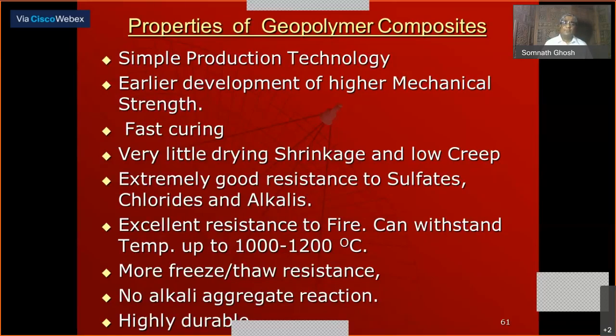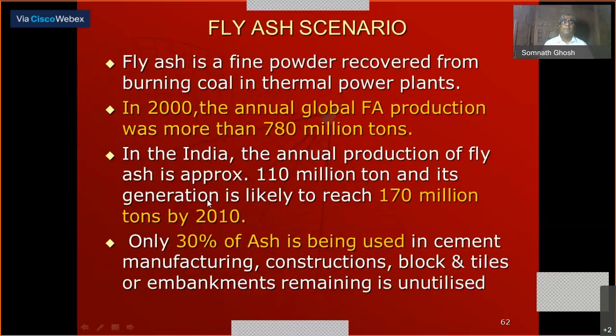The excellent resistance to fire, it can withstand that. Many PhD students worked on it, and ultimately found that it is good up to 1000 to 1200 degrees centigrade temperature. The freeze-thaw resistance is very good, and also alkali aggregate reaction, and it is highly durable. So all these things are much better than the conventional cement because of the polymeric structure. It is CSH gel there, here it is different, and here the gel is a polymeric one. That is why you are getting the huge difference, and you are getting better concrete.